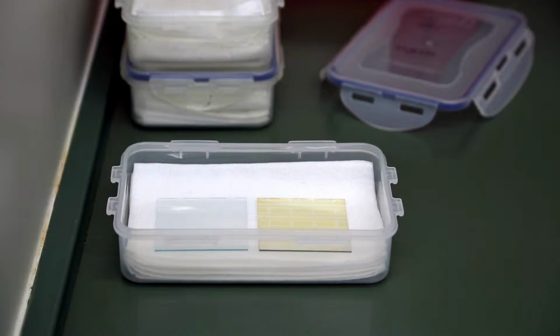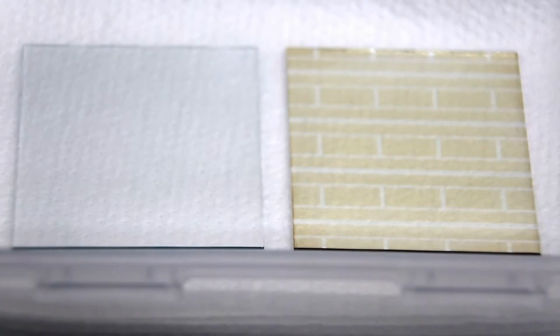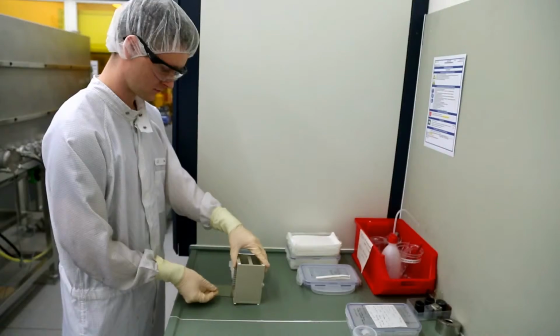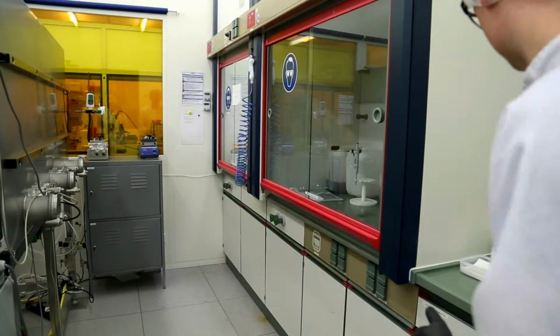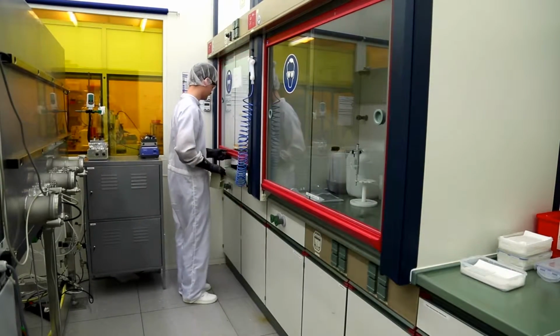The starting point is the anode, a coating consisting of indium tin oxide, abbreviated as ITO, deposited on a glass plate. The ITO is coated with a light-sensitive photoresist, which is developed only at the locations that are to be etched. The remaining parts will conduct the electricity later on, so the whole thing is similar to manufacturing a printed circuit board.